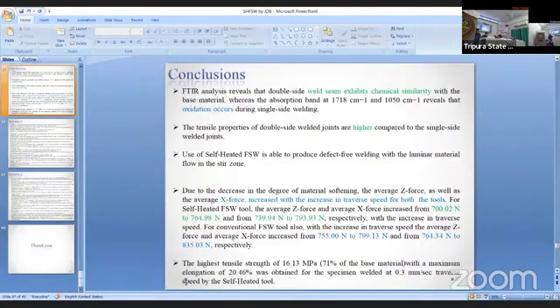So these are the conclusions that we can draw from the work. From the FTIR analysis, we could see that the double-side weld seam exhibited chemical similarity with the base material, whereas the absorption band from the FTIR analysis revealed that oxidation occurs during single-side welding. So that's why double-side welding was able to produce a better joint efficiency. And the tensile properties of double-sided welded joints are higher compared to the single-sided welded joints.